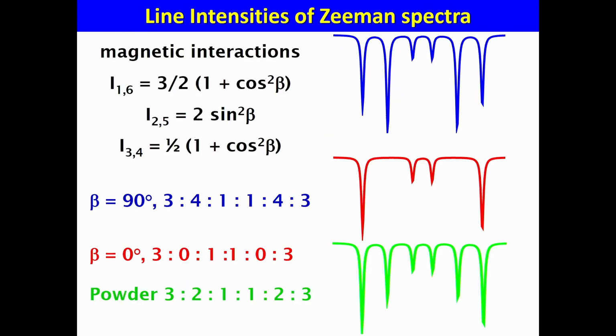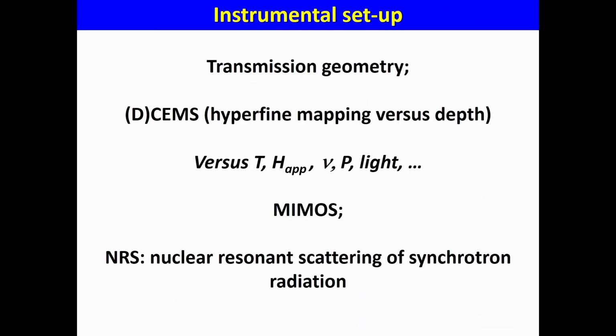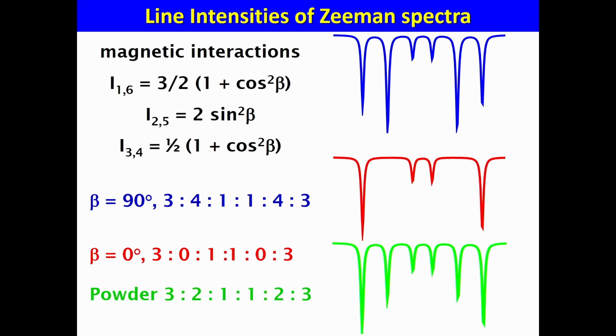So, okay. In the case of sextets, you can see a different situation. And what is important is that, back to the random distribution, powder, you have 3 to 1, 1 to 3. You have to remember that the external lines to inner ones ratio is 3:1. But for the intermediate lines, it may change. And of course, here you can see that you have the situation 3:4:1 and 3:0:1. That means you have 90 degrees between the direction of the magnetic moment and the direction of the gamma beam, and here it's 0 degrees.